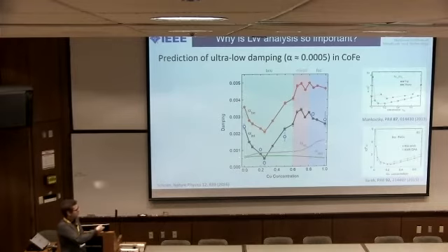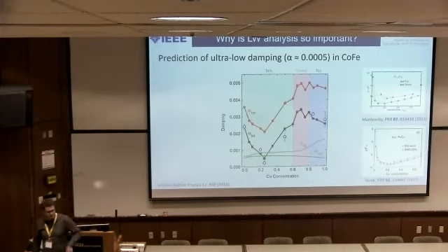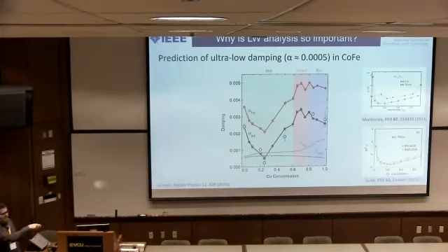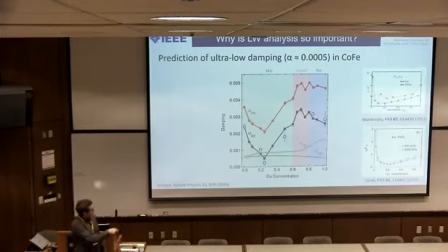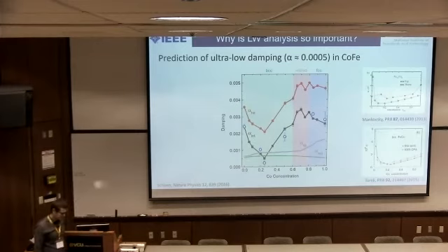But then we went in and we quantified the spin pumping contributions through a thickness series, for example, and that's shown in gray here. We experimentally quantified the radiative contributions. Those are the electrodynamic considerations I skipped over. And if we then subtract these two from the red data, we see that we get this nice minimum that's actually in agreement with theory. Because when we started off with this, we didn't know if the theory was wrong or the experiment was wrong or both were wrong. But what we see now is that we were actually able to confirm this theoretical prediction.